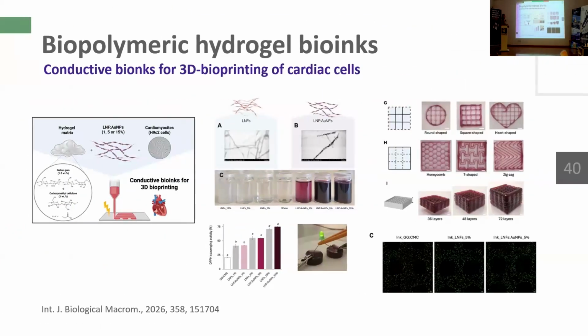And here, in this very recent work, we explore another feature of these protein nanofibrils. They can be used as templates for the synthesis of metallic nanoparticles. And here we use this approach to prepare hybrids of protein nanofibers and gold nanoparticles that were used as additives in a hydrogel matrix. And this was done to produce conductive bioinks for the bioprinting of cardiac cells. That is one of the properties relevant for this area. And apart from this, these bioinks present antioxidant properties. Probably this was the best bioink that we developed until now. We are able to produce quite different structures, and we were able to print at least 72 layers, keeping the stability and the structure of the construct.